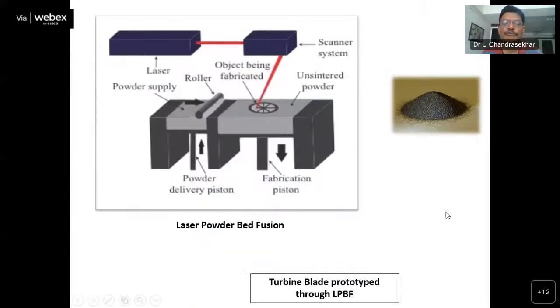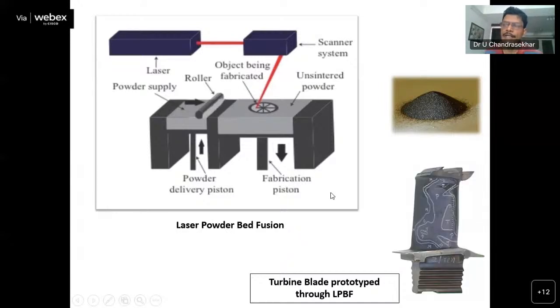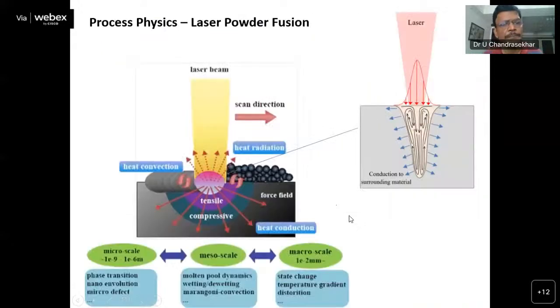So the fundamental process in this case is called laser powder bed fusion, wherein a high energy laser, typically a fiber laser, a continuous laser, is scanned on the surface of the powder, and because of the interaction between the laser beam and the powder, the particles get instantaneously melted and solidified as the beam is passing through. And eventually you lower the platform by an extent equivalent to one layer thickness, and the process is repeated ad nauseam till the overall height is achieved, leading to manufacturing of a turbine blade, which is shown on the right bottom. So this is a very complex phenomenon.